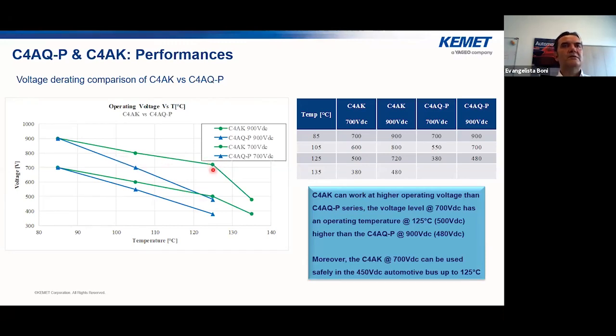And another important characteristic is that we can compare a C4AK at 700 volts with a C4AQP at 900 volts. The C4AK 900 volt is the same dimension as the C4AQP 900 volt. Of course, the C4AK 700 volt is smaller than the C4AQP 900 volt. And we can see here that at 125 degrees, the C4AK 700 volt can work at higher voltage than the C4AQP at 900 volt. And this is a great example of miniaturization due to the lower derating of the voltage.